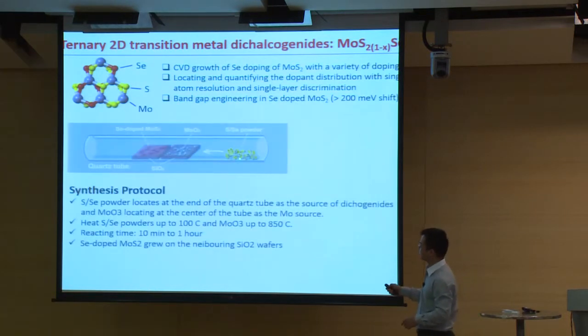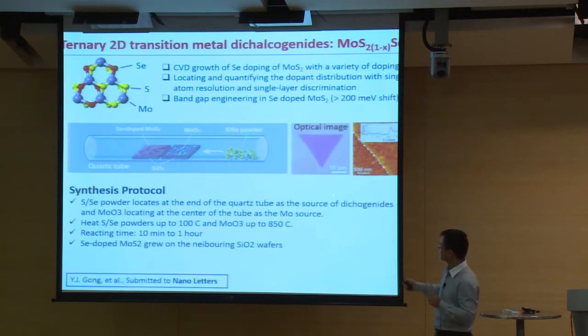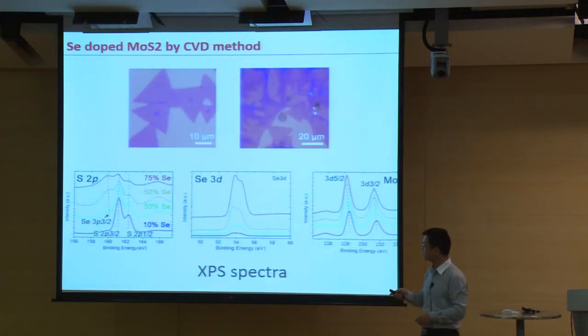So we start from the mixed powder of selenium and sulfur, and under similar conditions to the moly disulfide, we can get some flakes here. Okay, this is a single crystal monolayer triangle, selenium-doped moly disulfide. From the AFM, the thickness is from 0.7 to 0.8 nanometers, corresponding to a monolayer. And this is our synthesis protocol. We can also grow some polycrystalline and also film-like films for the selenium moly disulfide. So from the XPS spectrum, from 10% to 75%, you can see the peak from the selenium comes out, and also the selenium 3d peak becomes stronger and stronger.